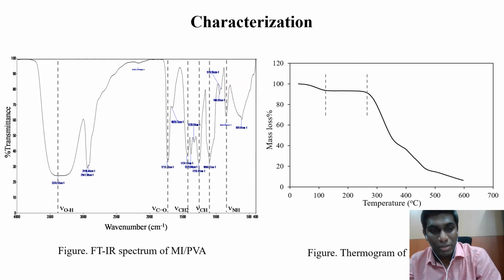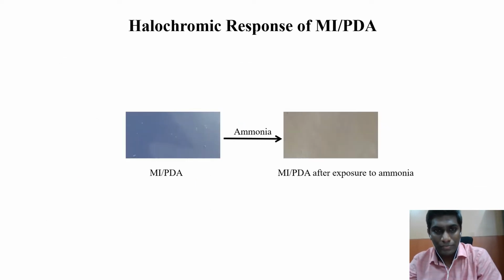The stretching vibrations observed for the mixed indicators clearly suggest that the halochromic thin film is successfully prepared. On the other hand, the degradation patterns observed in the thermogravimetric analysis also suggest that there is a successful incorporation of the halochromic dyes. And this is the halochromic response of the mixed indicator MI/PDA halochromic thin film. The raw thin film itself shows a light blue color which changes into a gray color when we expose the thin film to the ammonia.